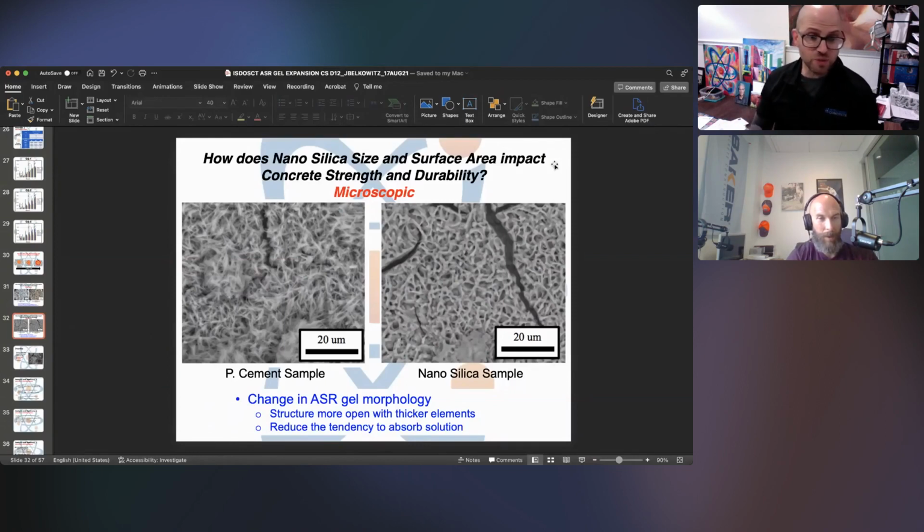And in doing so, we increased the space between those needles. And what we also do is change up the viscoelastic properties, the elasticity of the gel too. So again, it's not just a chemical approach, but this mechanical approach is it's not going to imbibe as much water. When it does try to expand, it's not going to be able to expand.